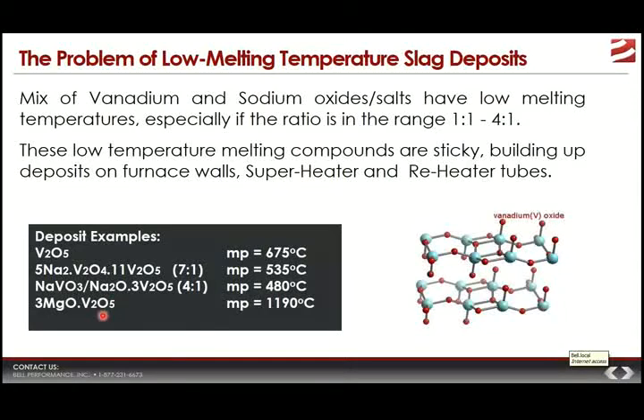Now, note this last one. When you take out the sodium and start adding magnesium into it, suddenly you get a magnesium vanadium oxide compound. The important thing to note is that the melting point, when you add magnesium to it, actually skyrockets up to close to 1200 degrees. A very important consideration for fixing these problems, as we'll see later.